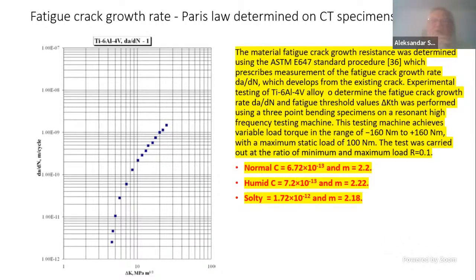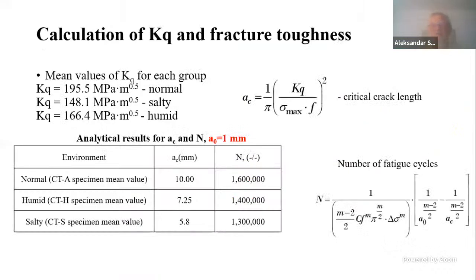It was done according to the standard procedure, and as the result, we got these pairs of C and m for normal, humid, and salty conditions, and once again in the same order of the effect. So humid is less damaging than salty. And you will see this also by calculation.